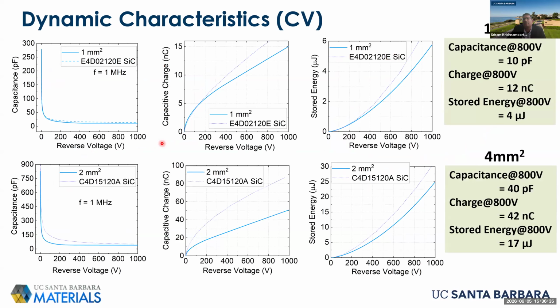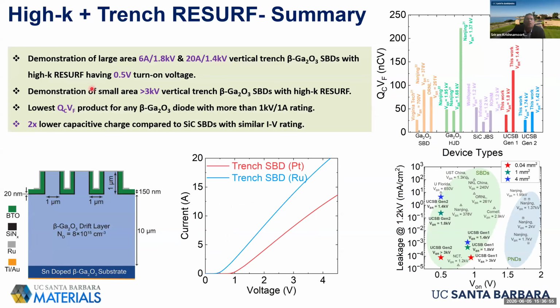And what is now more exciting is we did some capacitance measurements, estimated the stored charge in these diodes, and tried to compare it to silicon carbide bare die off-the-shelf components, and we are able to get lower charge, lower stored energy in these diodes compared to silicon carbide. So we actually have the lowest stored charge forward voltage product of any gallium oxide diode, with more than 1 kilovolt, 1 amp rating in this trench high K RESURF diode approach.